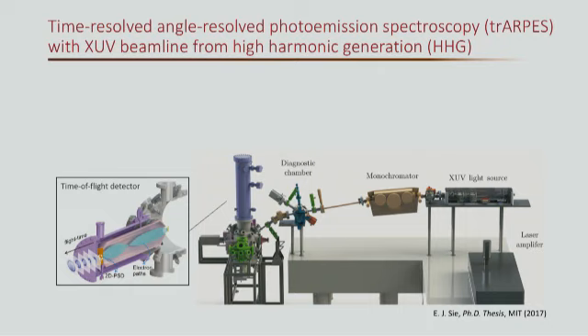If you are familiar with trARPES, many groups actually use the so-called hemispherical detector. But here, we use the time-of-flight detector because we can really get the three-dimensional information about band dispersion at one time. So the three dimensions are basically the two in-plane momenta, kx and ky, and then the energy axis, the vertical axis, which is calculated from the time it takes for the electron to travel from the sample to the detector, and then converted to energy.